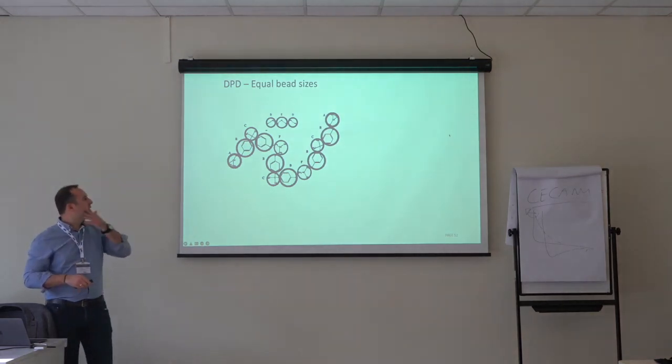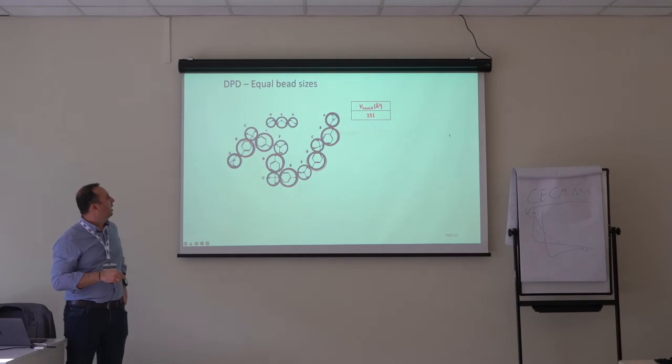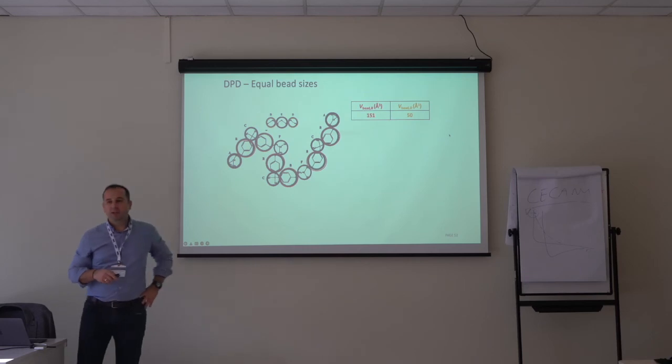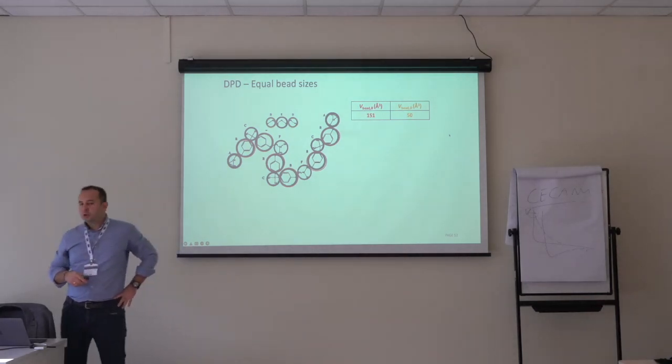This was the system I was working on in my PhD, and we coarse grained it in such a way that the beads are quite different. For example, the cyclic ones are like 150 cubic angstrom, but the small beads, with 2 heavy atoms, are like 50 cubic angstrom. So that is a factor of 3 difference. That's a problem, so how do we solve this?